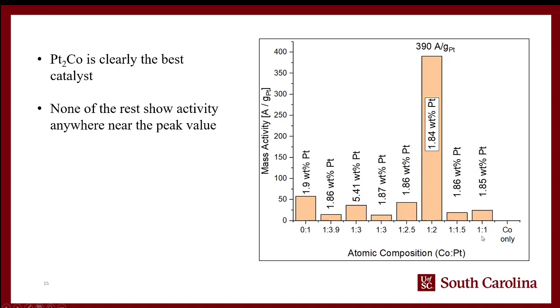And so we went from, originally it was 1 to 1, 1 to 2, and 1 to 3. We saw this huge jump between, 1 to 1 was low, 1 to 2 was huge, 1 to 3 was low. So we wanted to check sort of a middle value here. So we did 1 to 2.5 and 1 to 1.5, and there's not really a peak here. You could argue maybe a little bit of 1 on this side, but more or less this 1 to 2 is the perfect composition. And you would have to get very, very fine, maybe 1 to 2.1 and 1 to 1.9 or something like that to start seeing a peak fall on either side.